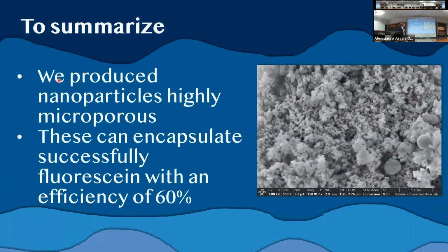In conclusion, we managed to produce the silica highly microporous nanoparticles with fluorophore encapsulated into them. These particles seem to be able to retain up to 60% of the fluorophore that was added, which is great, meaning that we have a possible sensor for our endoscope.